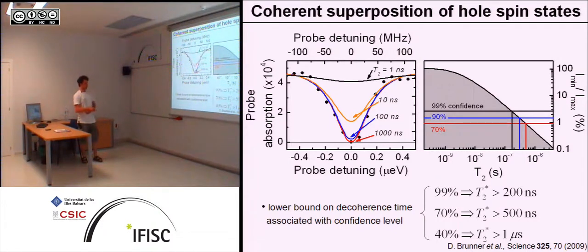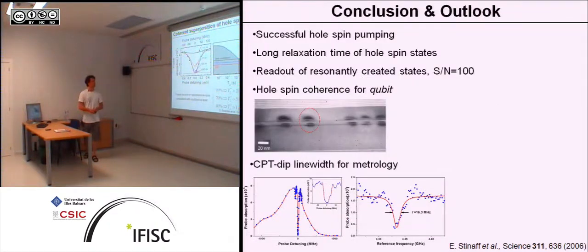I mean, the electron spin, whatever you do, unless you do spin echo techniques or something else, you can never get the coherence time above 40 nanoseconds. So to get around 1 microsecond just by choosing a different system with a different Bloch wave function, I think really shows the fundamental difference of the two quantum mechanical systems, and how this quantum dot actually gives you access to the quantum mechanical physics which are happening in this material. And this is why I think it's such a nice experiment, because you don't only get the results, but you can also show the fundamental difference of very simple quantum mechanics.